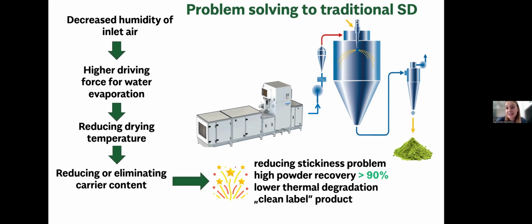And what is the effect of all of it? We can reduce the stickiness problem. This is the most important thing, so we can ensure a satisfactory powder recovery, and we can omit the problems that we can have then with handling of powders. In some cases, powder recovery that we observed in these studies was very high, even over 90%.